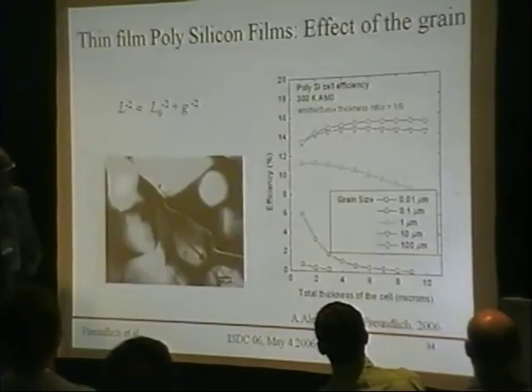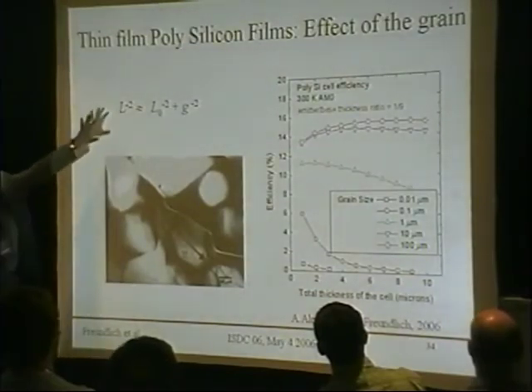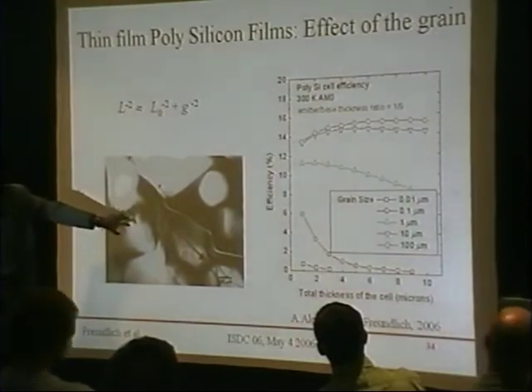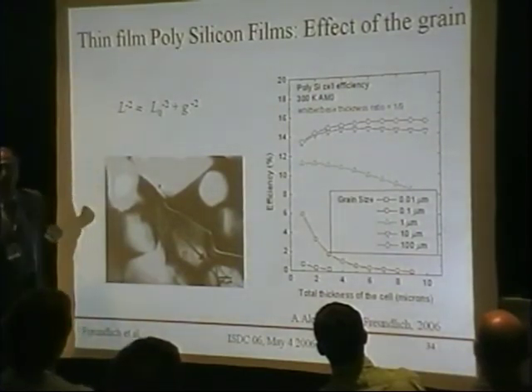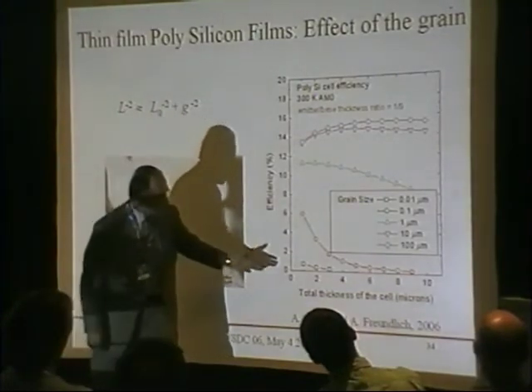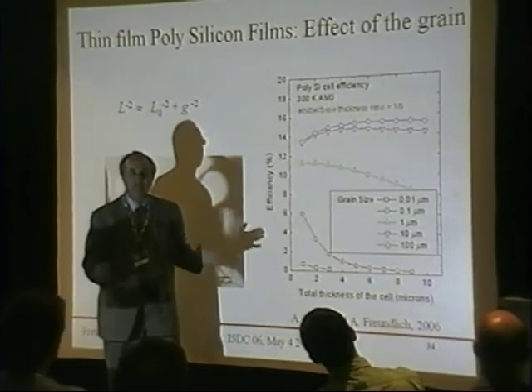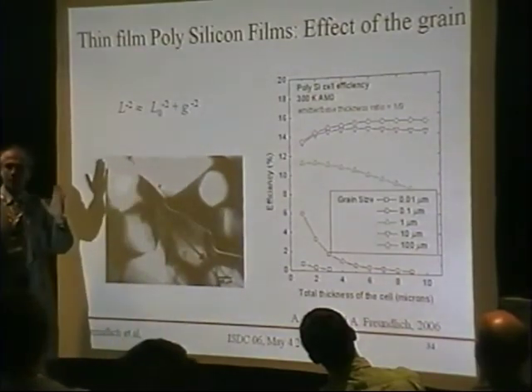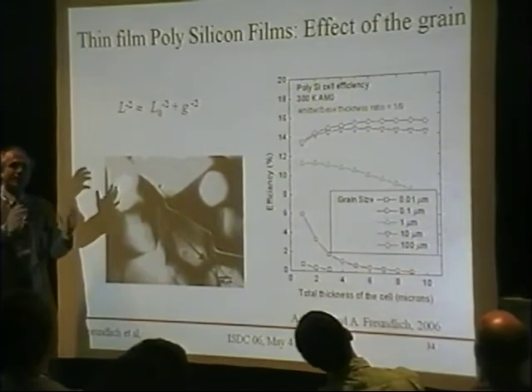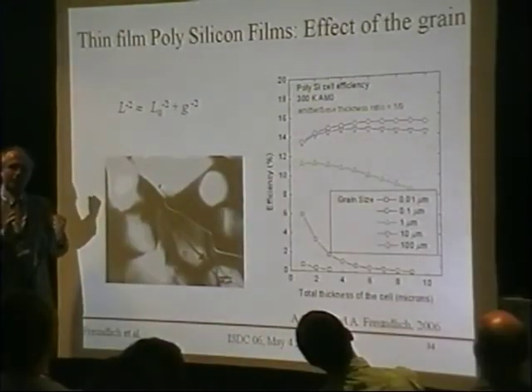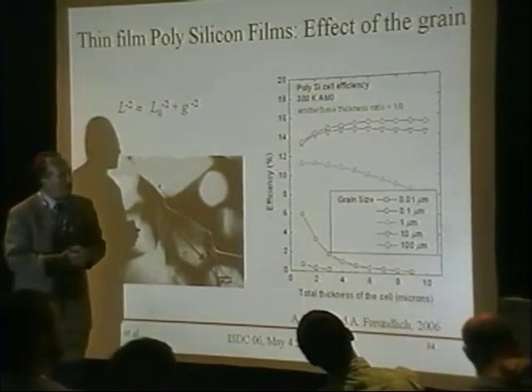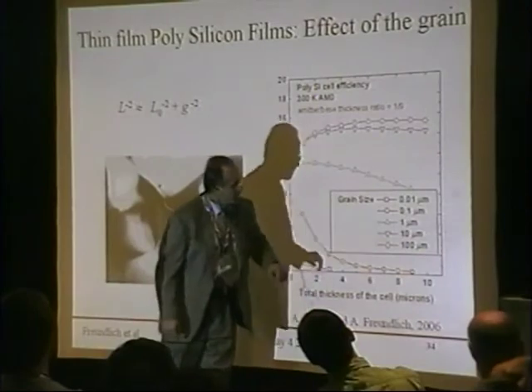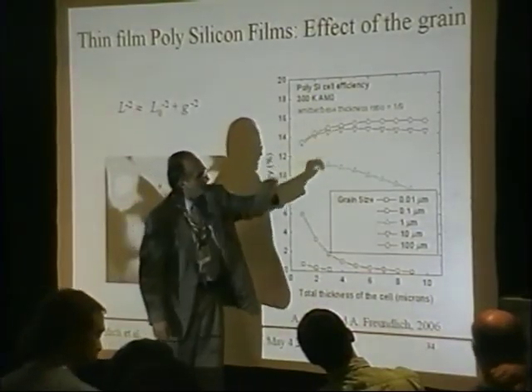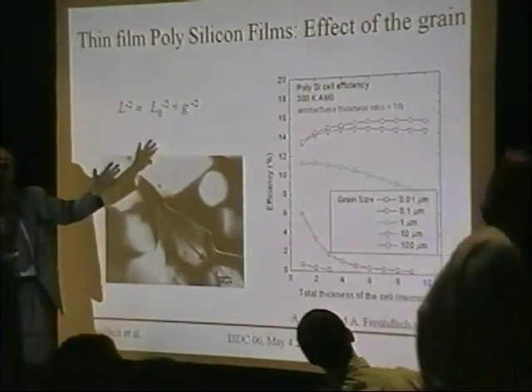Next. Now, on the moon our samples are going to be polycrystalline at best, because we're going to fabricate them at relatively low temperature from relatively poor materials. Similarly to the radiation effect, if the grain size becomes smaller, the diffusion length will also go down. But one technique that one can use is to reduce the device thickness. You lose some efficiency because you're not absorbing as much, but you're not losing the collected electrons. Here, as a function of the grain size, I have plotted the efficiencies that one will get in silicon. These are practical efficiencies. We'll see that in a minute.